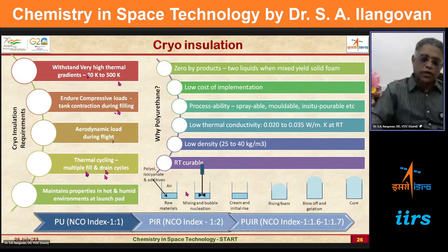So this also it has to withstand. So polyurethane is one of the finest materials. How we are making it is that the raw materials are analyzed and accepted, we mix them, and there is nucleation, and we also add the foaming agent. The volume rises as the foam rises, then gelation takes place. After curing, it is able to maintain the rigidity, with closed cells, then the volume has gone up, so density is very low, and thermal insulation is brought about, right?